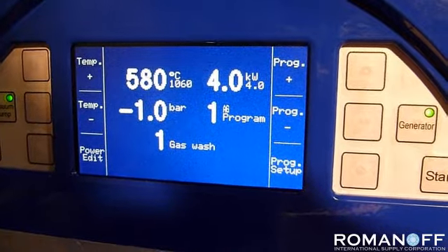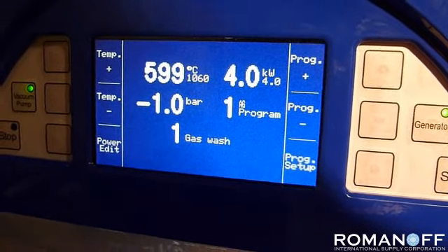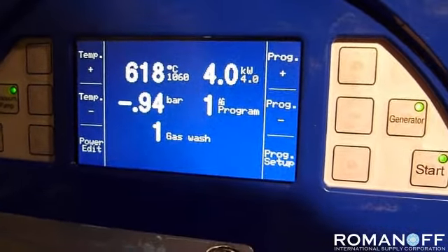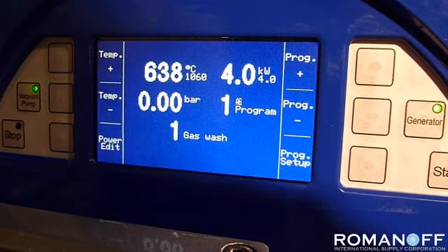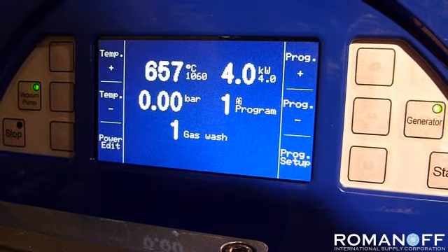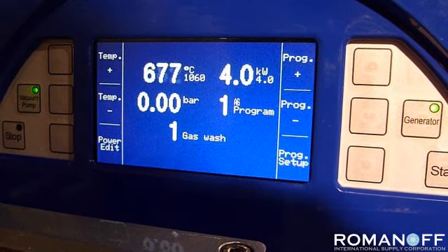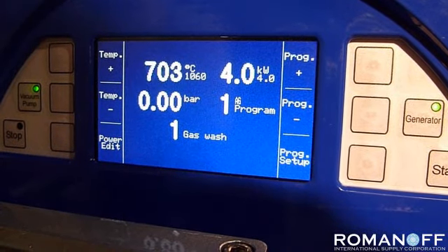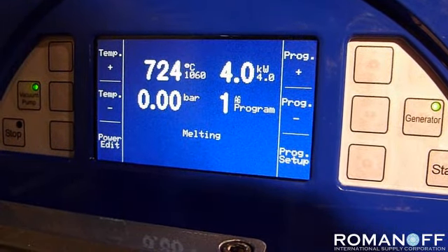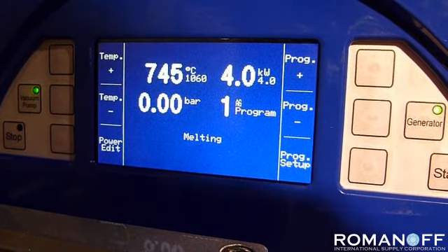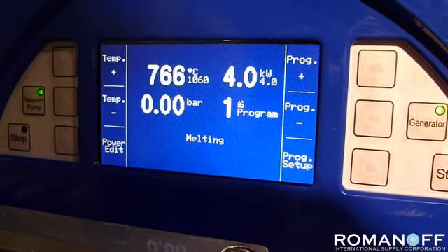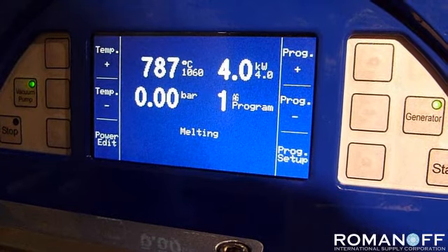While the metal is melting, I just want to point out that the machine can produce up to 8 kilowatts of power for rapid melting. At this moment we're only using 4 kilowatts of power for gold and silver alloys. Generally you would use 8 kilowatts of power for platinum, which is a higher melting point metal. The casting chamber is completely water cooled.